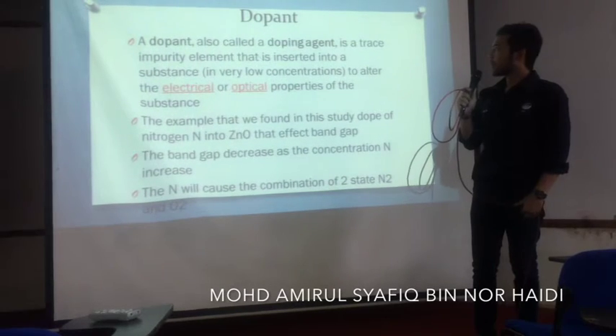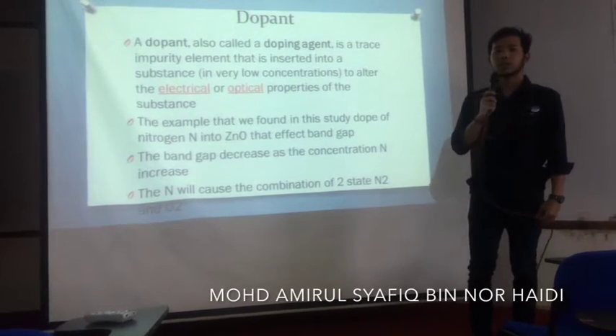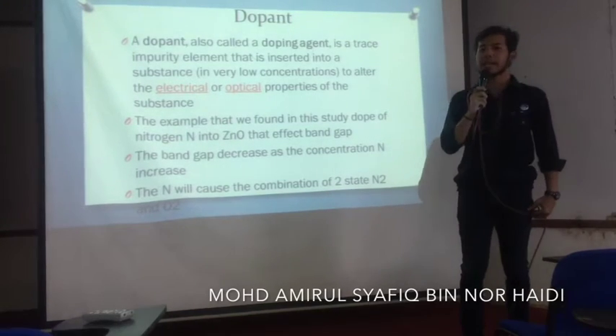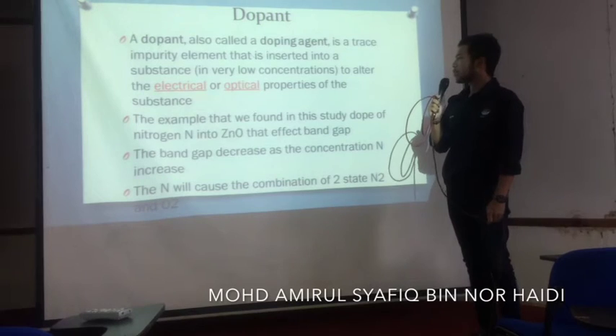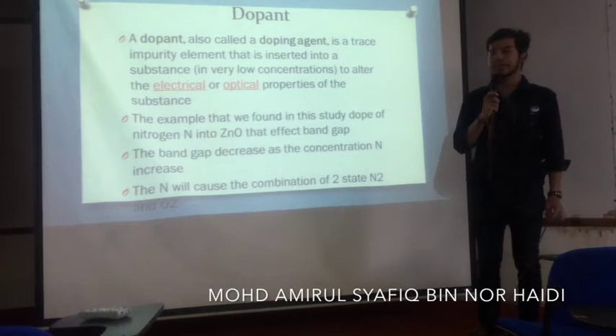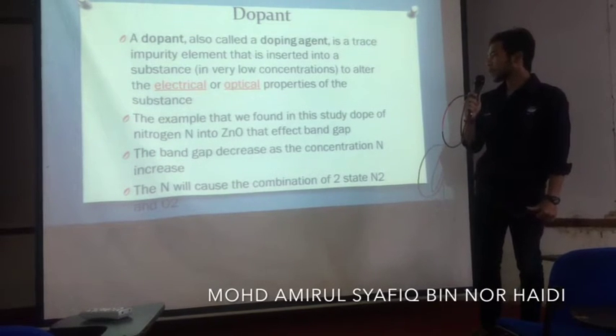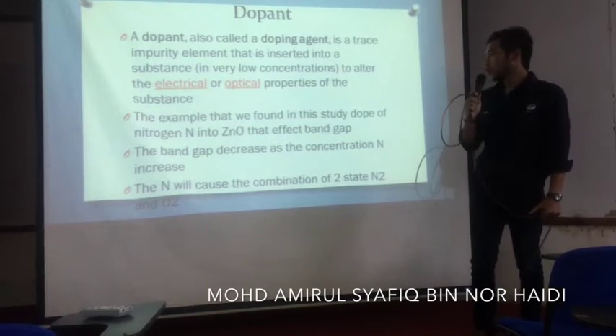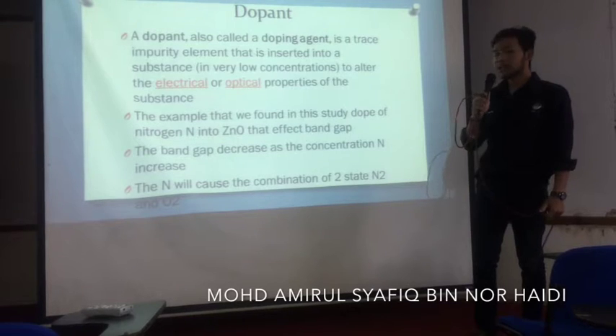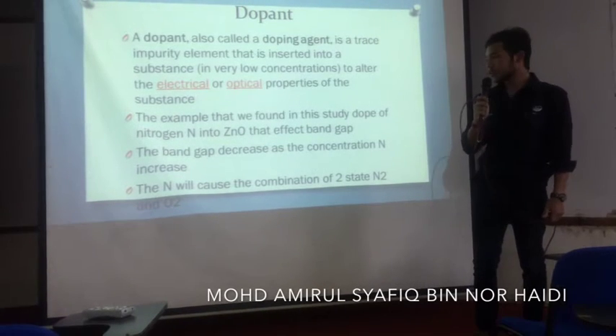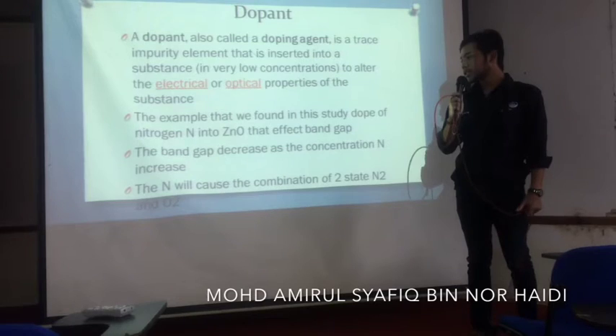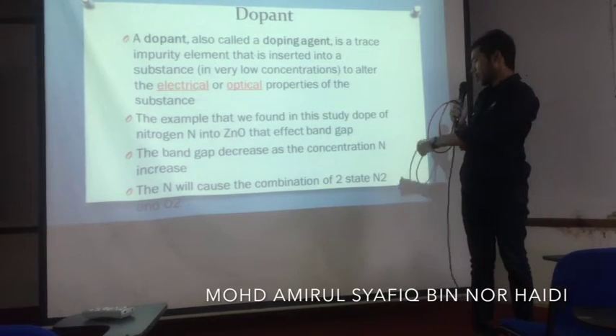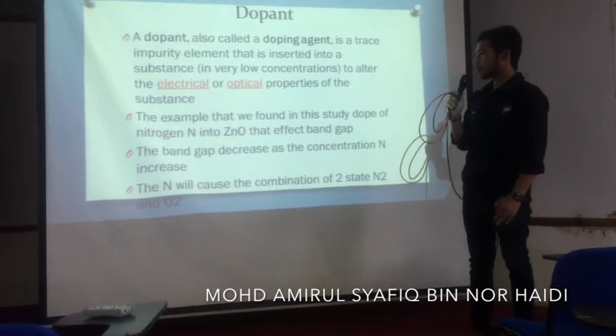First, the effect of doping, also called the doping agent. It is a trace impurity element added to a substance to alter its properties. For example, in this study, doping nitrogen into zinc oxide affects the band gap. The band gap decreases as the concentration of nitrogen increases, because nitrogen causes the combination of two states: nitrogen 2p and oxygen 2p.